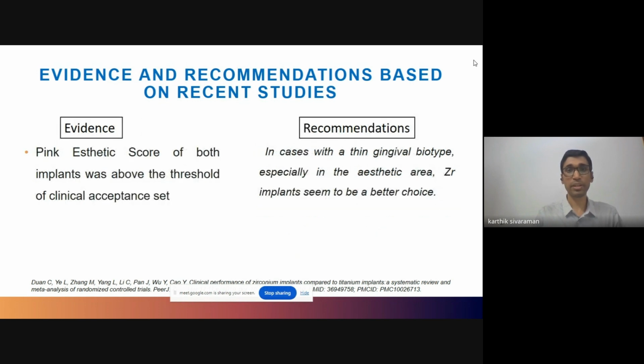Now, the evidence and recommendations pertaining to the pink aesthetic score. Initially, I mentioned that the clinicians and the patients have a view that being a ceramic material, zirconia is a very aesthetic material. So this also assesses the pink aesthetic score of both sets of implants, titanium and zirconium, and both of them were found to be acceptable. So the authors recommended that in cases with a thin gingival biotype, especially in the aesthetic zone, zirconia implants could be considered to be a better choice. So it implies that there is nothing wrong with titanium as such in terms of aesthetics.